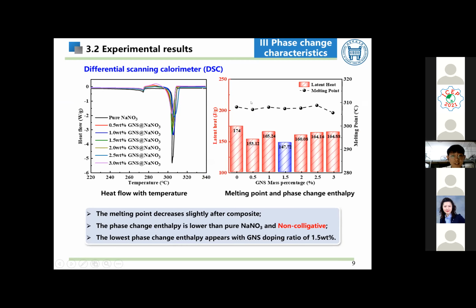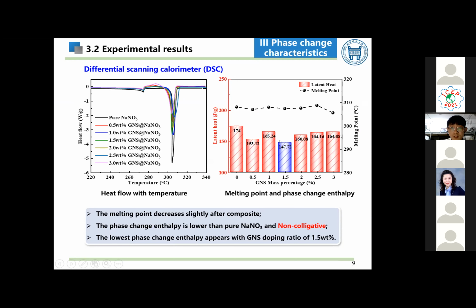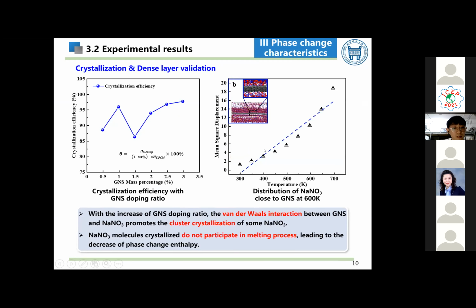The melting point and the latent heat are as follows. As can be seen from the figure, the melting point of the composite decreased slightly, yet the phase change enthalpy decreased significantly. Interestingly, we found that the phase change enthalpy has a non-colligative decrease. The lowest phase change enthalpy appears with a doping ratio of 1.5%. To visualize the change in enthalpy, we defined the crystallization efficiency theta. As shown in the figure, theta of all the composites are lower than 100%. The lowest value appears when the doping ratio is 1.5%, which is only 86%.